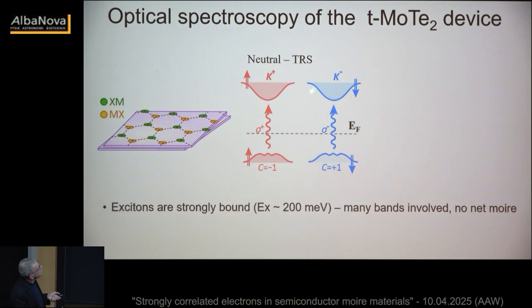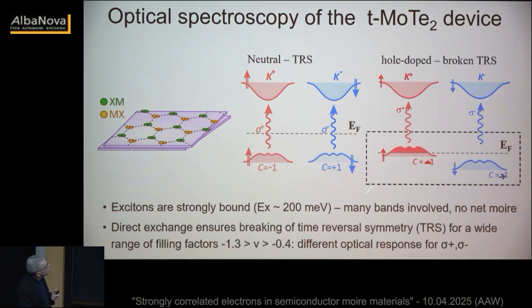So if the system is charge neutral, again, the story is almost the same. So we have sigma plus and sigma minus excitations, the Fermi energy is in the middle. The excitons are strongly bound, not as strong as in molybdenum disulfide, but it's still about 200 meV. And there is no net moire for excitons because exciton binding is so strong that even if you have moire bands, it averages out. All right, so what happens is that when you hole dope the system, then we spontaneously magnetize the system, and this is what I'm going to show you.